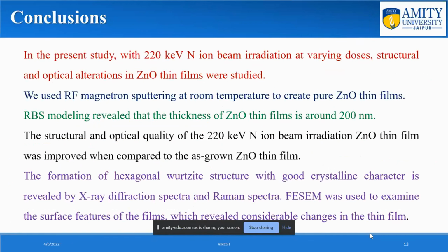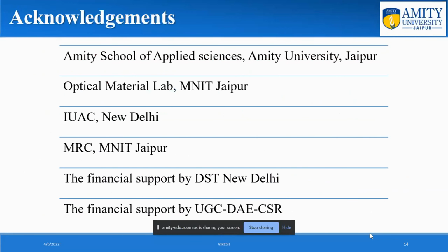The structural and optical quality of the ZnO thin film was improved with 220 keV nitrogen ion beam irradiation when compared to the as grown ZnO thin film. The formation of hexagonal wurtzite structure with good crystalline character is revealed by the XRD spectrum and Raman spectrum. FESEM was used to examine the surface features of film, which reveal considerable changes in the thin film.